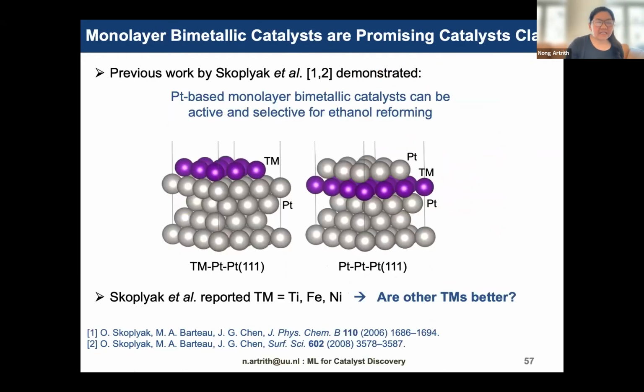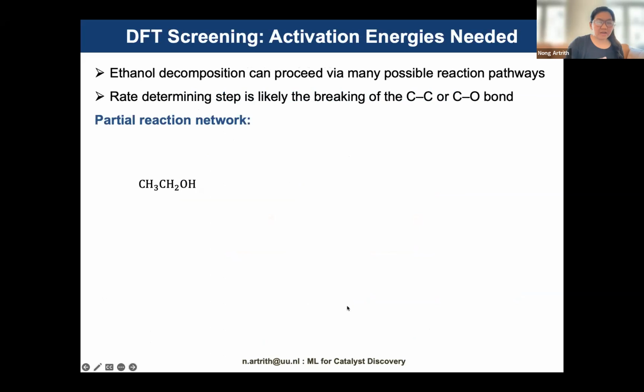So let's take a look at the data that we have from our experimental collaborators. Together with the Jingguang Chen group at Columbia University, we found that for the ethanol reforming they use in the experiments, there are not many models. They use only 3 types of metals, titanium, iron, and nickel. On the left-hand side, this is the transition metal, in purple, and platinum in gray. Another model is a platinum monolayer on top of the cheap transition metals, where they use titanium, iron, and nickel in these 2 models. So in total, they only have 7 data points. But are there other metals that work better, or cheaper, or equally well as these 3 types of materials? So we started to do DFT screening to find activation energies of all paths.